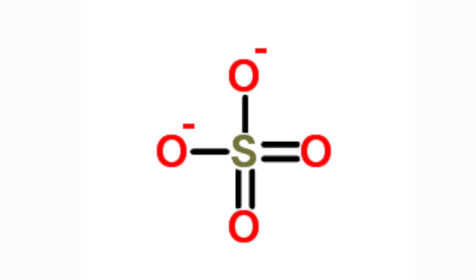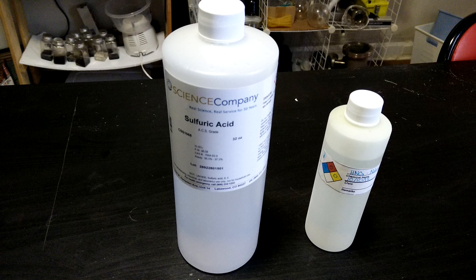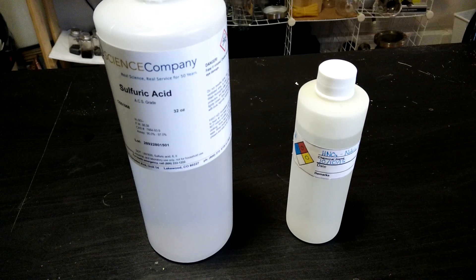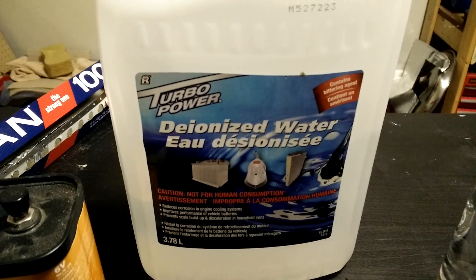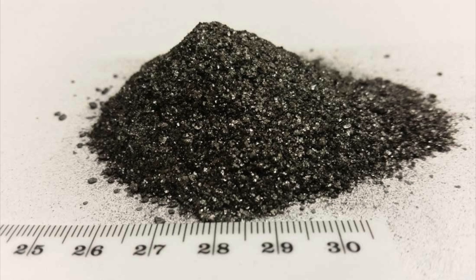In this video, we'll be looking at one of the last cases, though we'll explore others in the future. Specifically, we'll be intercalating sulfuric acid. To do this requires only a few things: 96–98% sulfuric acid, concentrated nitric acid, a lot of deionized water, and of course, our graphite.